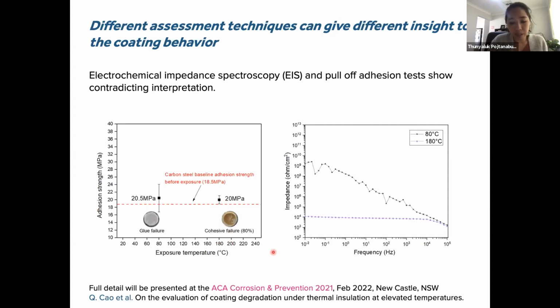But we also took the sample and ran EIS at that particular temperature. The sample is a vertical pipe, so we have a smaller PVC cup attached onto the pipe, creating a reservoir of the electrolyte where we do the EIS. On the right-hand side, this shows the difference in the EIS run on the pipe section at 80 degrees and 180 degrees. We can see a significant difference in the coating behavior from the EIS data. The test is still ongoing in terms of the project.